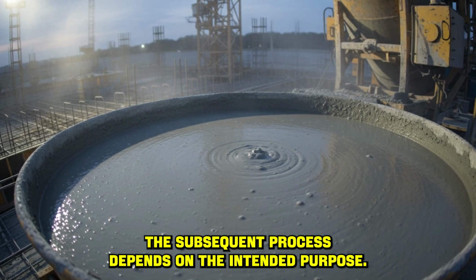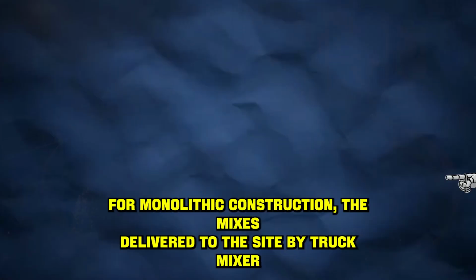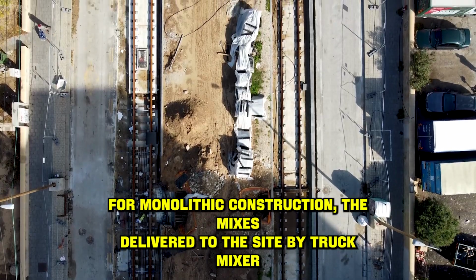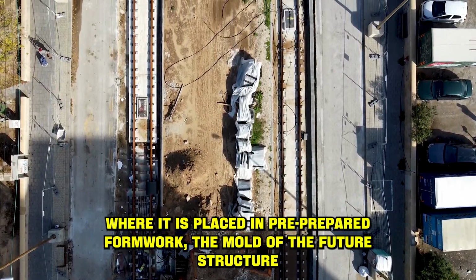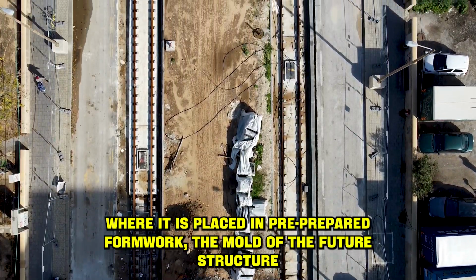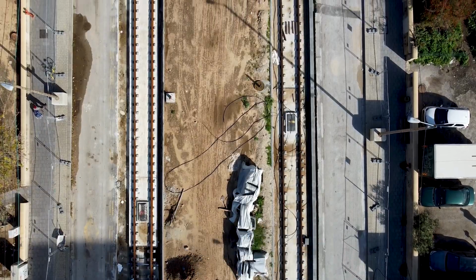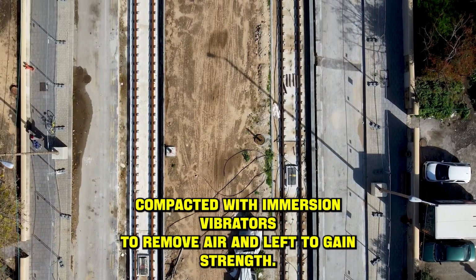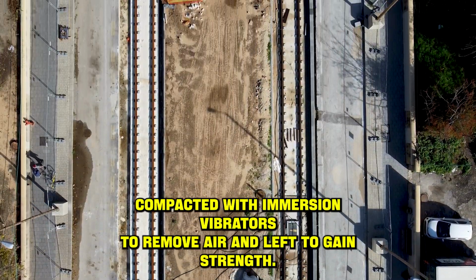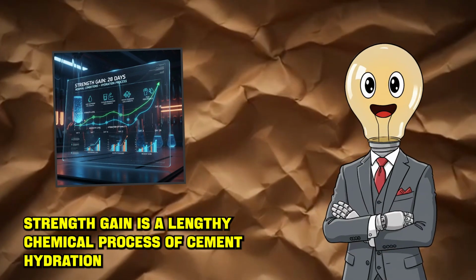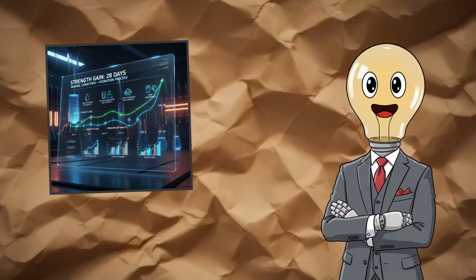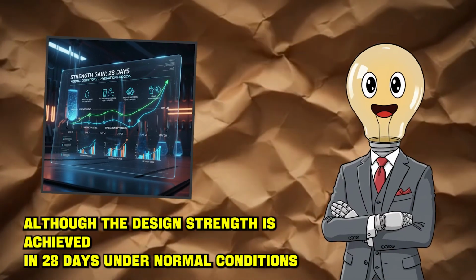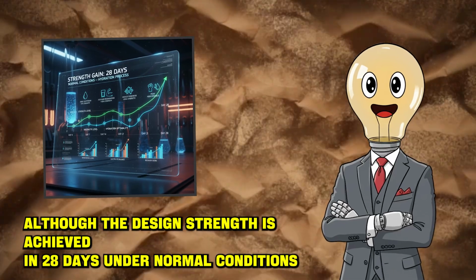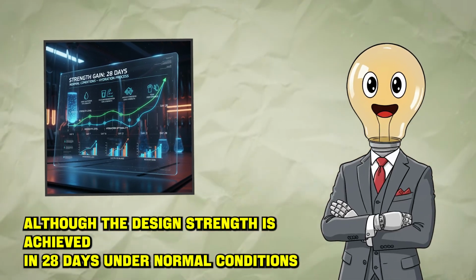The subsequent process depends on the intended purpose. For monolithic construction, the mix is delivered to the site by truck mixer where it is placed in pre-prepared formwork, the mold of the future structure, compacted with immersion vibrators to remove air and left to gain strength. Strength gain is a lengthy chemical process of cement hydration, lasting weeks and months, although the design strength is achieved in 28 days under normal conditions.